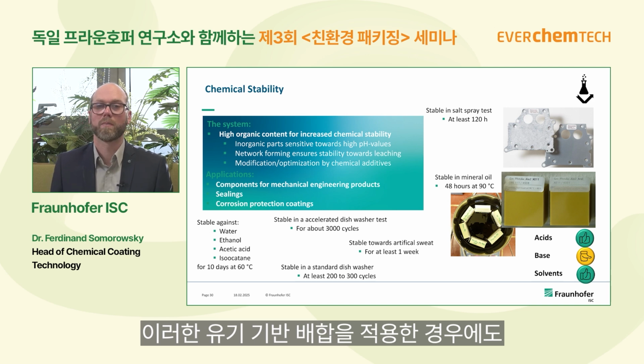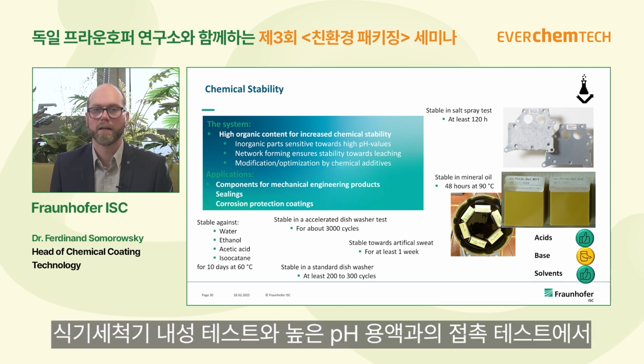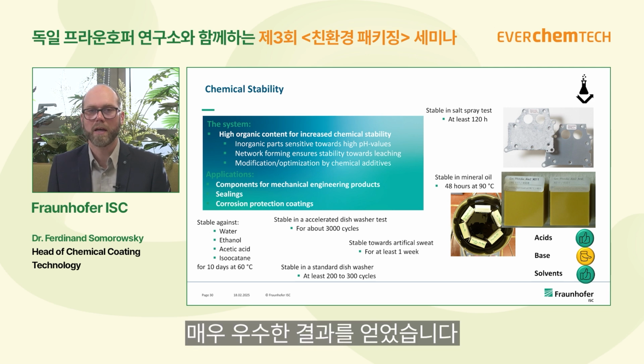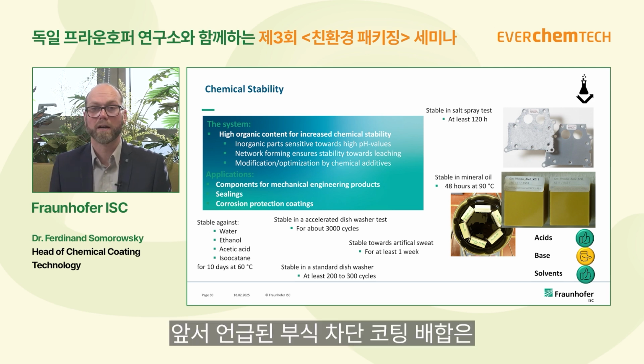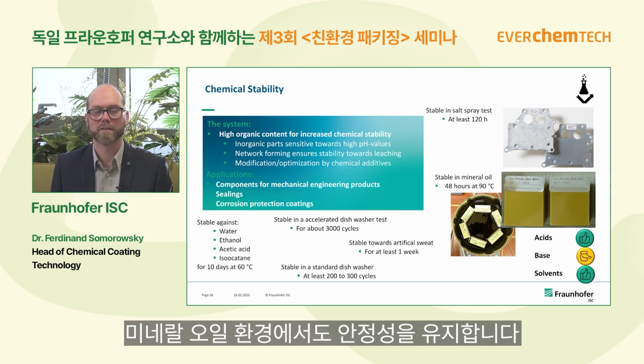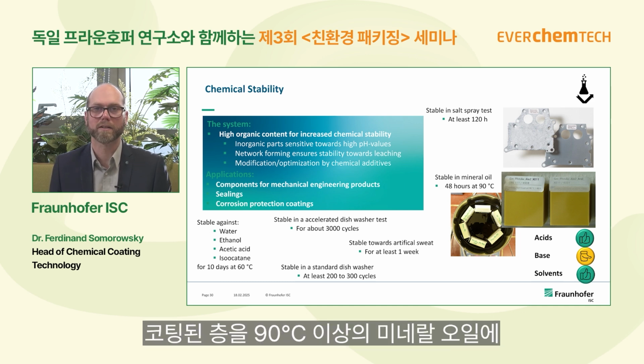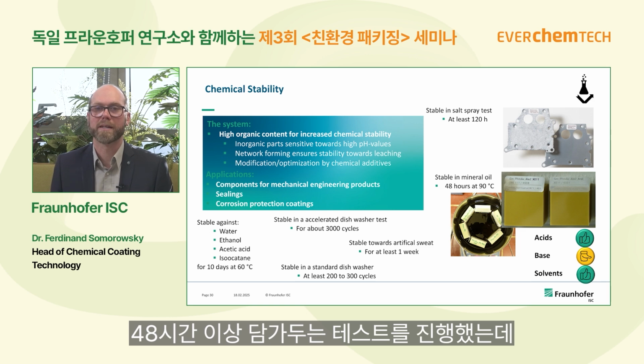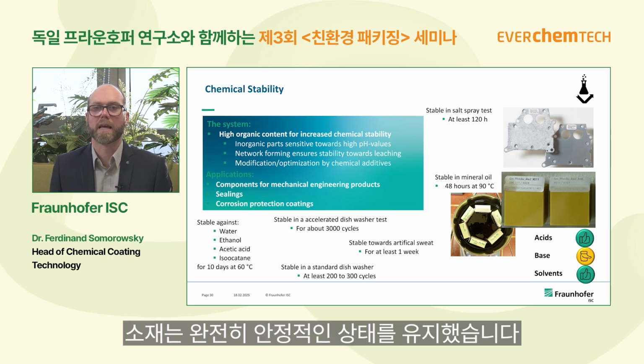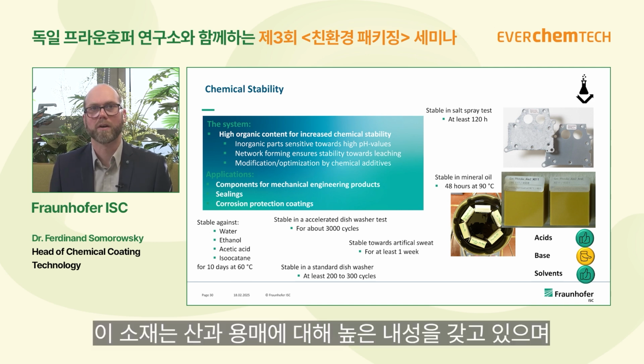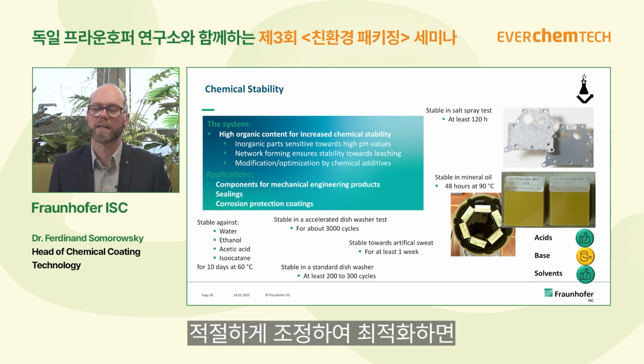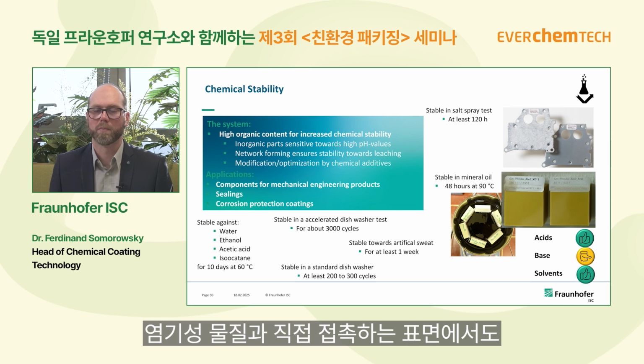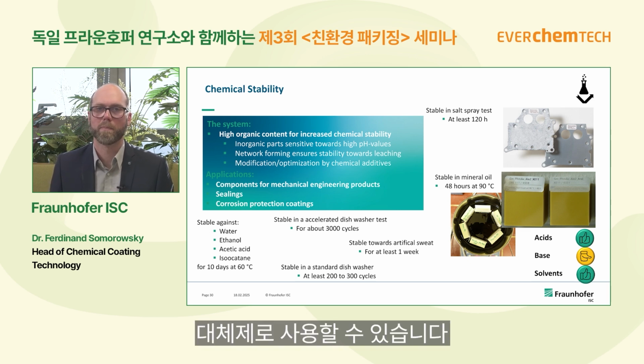But even with the Ormocer, we can achieve very good results in dishwasher tests and contact tests with media with a high pH value. Then of course the mentioned anti-corrosion formulation, it's also stable towards mineral oils. We cooked Ormocer layers in the mineral oil for more than 48 hours at more than 90 degrees, and it's completely stable. So when we summarize that a little bit, the Ormocer is stable towards acids, towards solvents, and when it's adjusted and optimized, it can also be an alternative for surfaces that have direct contact to basic materials.